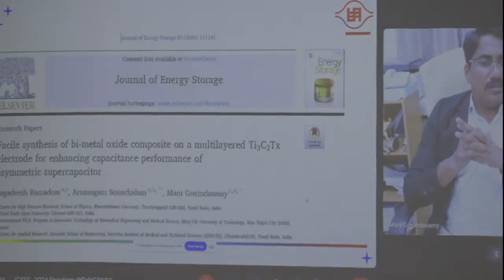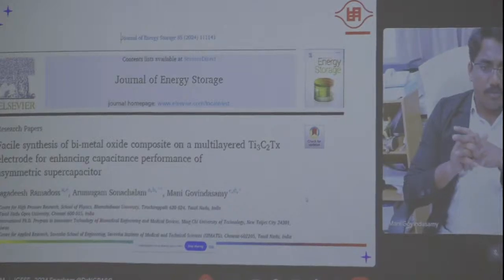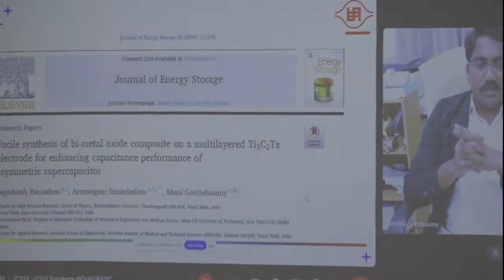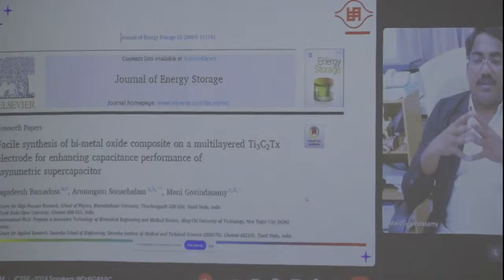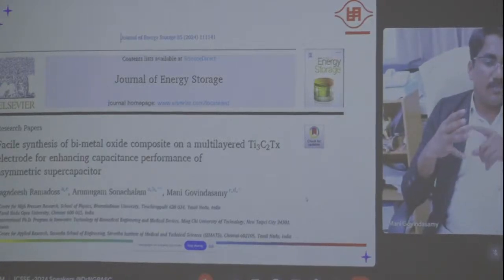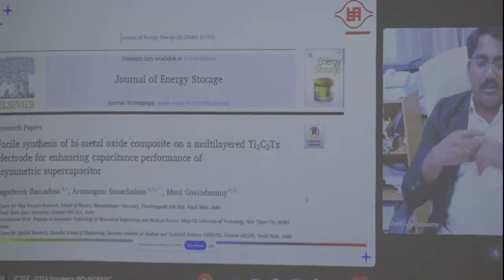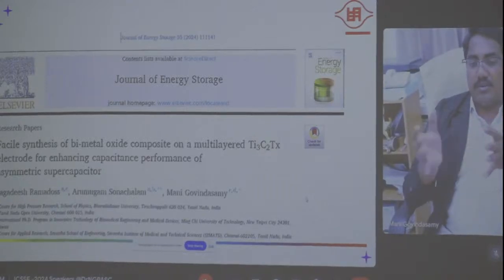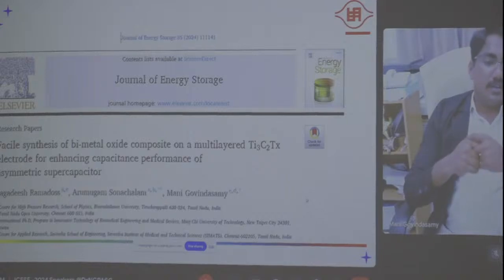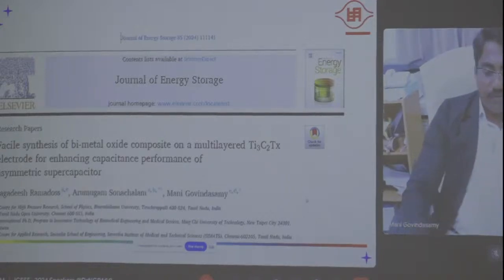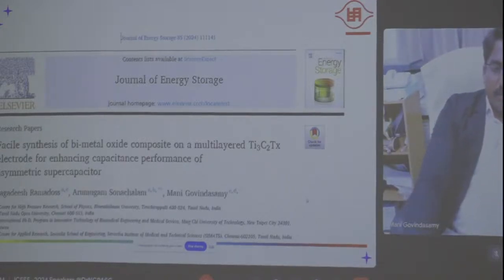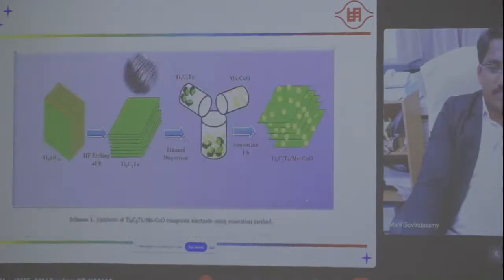And in this work we develop bimetal oxide doped with multi-layer MXene. Our concept is that the base material is MXene. Then we can combine it with different kinds of metal oxides, metal sulfides, and doping. When we combine with 3D and 2D layered materials, we can enhance the energy density as well as power density. That's why we develop bimetal oxide combined MXene for supercapacitor applications.